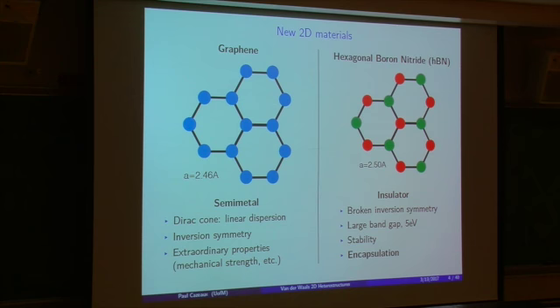And as you can see, it has a slightly different lattice constant of 2.5 angstrom. And both of these structures are really stable. They are really two-dimensional, and all the bonds in plane are fully occupied. And this means that we can potentially put them on top of each other and start to play with such a structure, having just a very little interaction between the two.